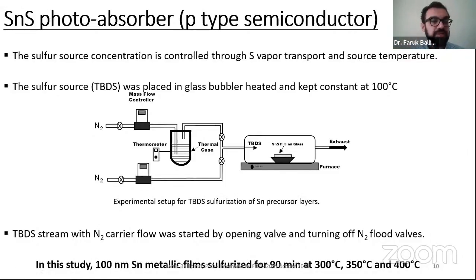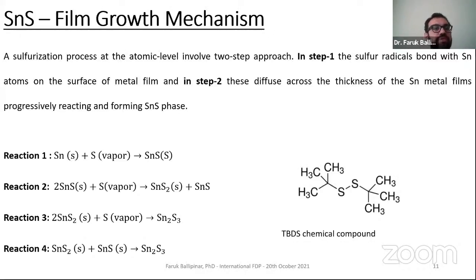So in this research, a 100 nanometer RF sputtered metallic film was sulfurized for a fixed time, 90 minutes, at various temperatures: 300, 350, and 400 degrees. The sulfurization thin sulfide film growth has two steps. Basically, in the first step, the sulfur atoms bond with tin atoms, firstly on the surface of the film, then diffuse across the thickness of the metallic layer. In reaction one, tin started to sulfurize with sulfur vapor and becomes tin sulfide. The critical step is we want the pure, highly crystalline and highly dominant tin sulfide. So time optimization is really important between reaction 1 and reaction 2.